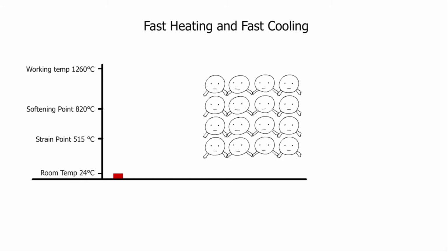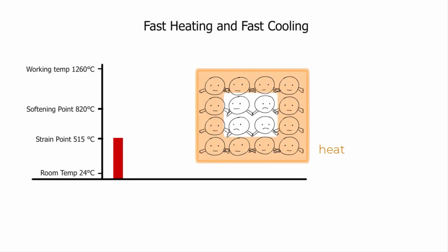Let's say this is an inch thick glass and then we are heating it with a torch flame. When the outside temperature hits 515 degrees Celsius, the glass molecules on the surface are ready to change their structure. But the molecules inside is still cold and hard, and the gap between the inside and outside causes internal stress. The stress can crack or chip the glass.